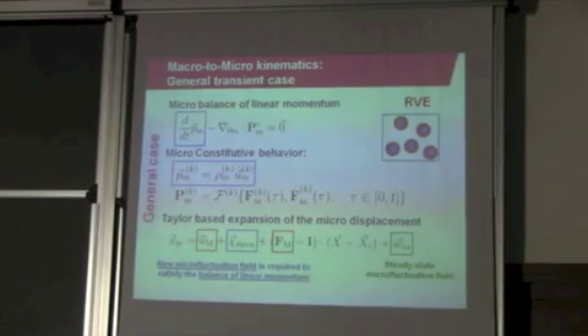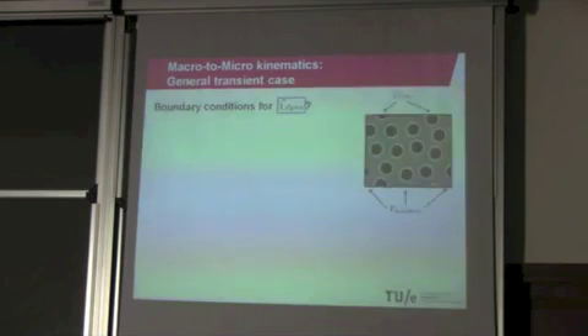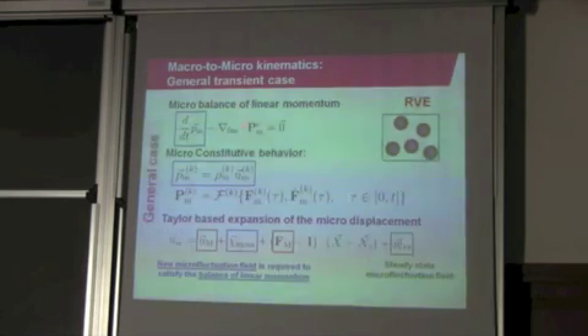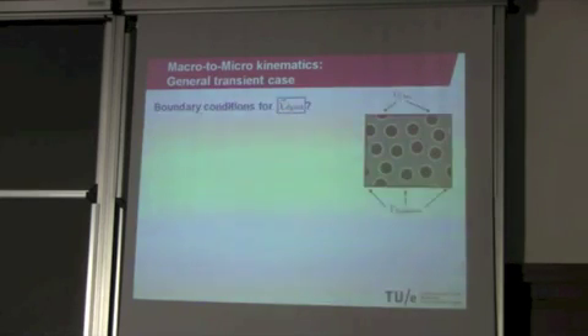And on top of that, we now have an additional field that arises from the fact that the microstructure is dynamic. So there is some response in the displacement that differs from this microfluctuation field in the steady state condition, and this is exactly the field that will be needed to satisfy the balance of linear momentum. Okay, and by the way, this is a very important ingredient in the whole framework, because that's actually the field that will make the whole trick at the end. Okay, so I now need to solve this linear balance of momentum problem, where now only this dynamic microfluctuation field is unknown, since this I already solved for, this I know, and these are coming from the macro scale. So I need the boundary conditions for this one. You again can choose different ones, but that's what we have chosen.